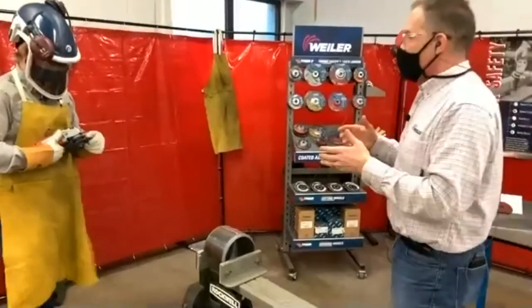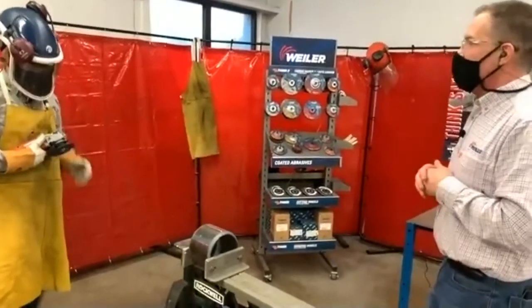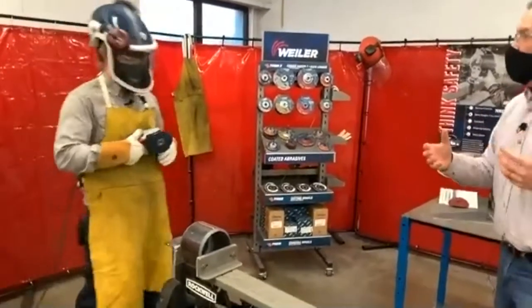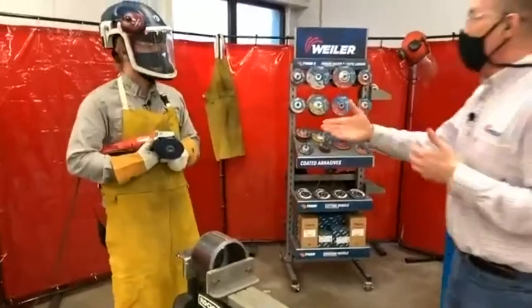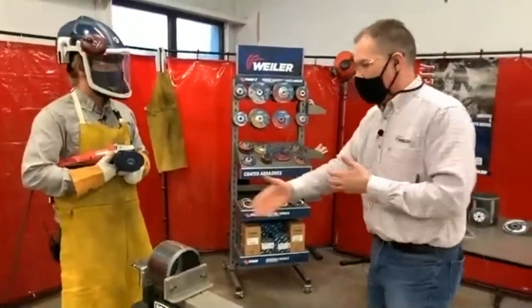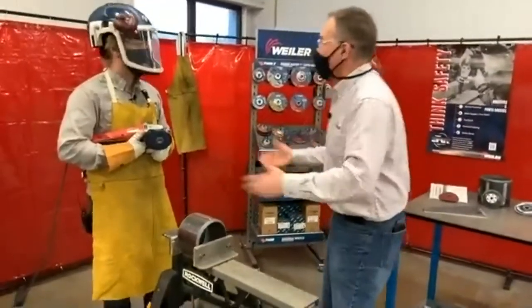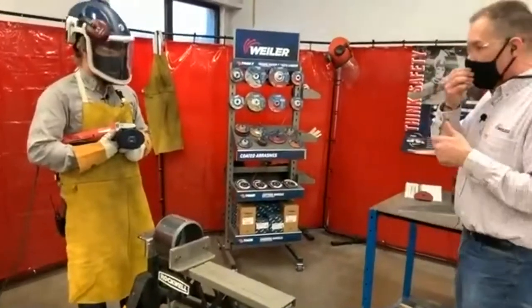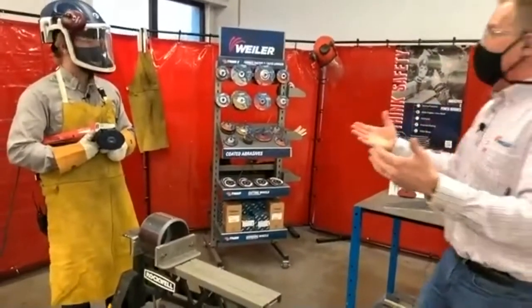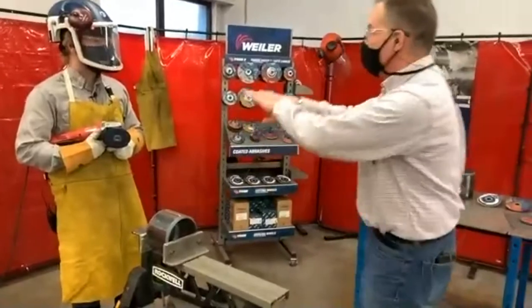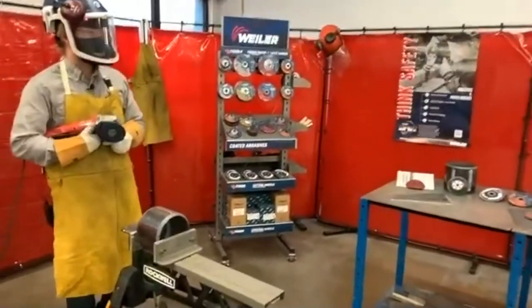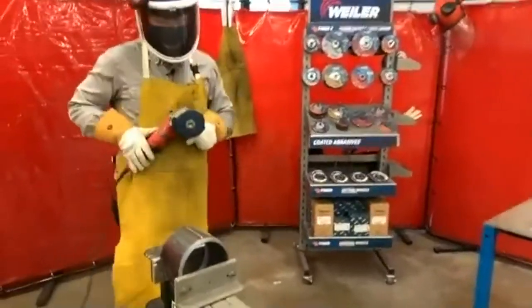And now again, the big difference here is this is our flexible backing pad, versus the medium or harder backing pad that we would use on a flat, more consistent surface. But again, it shows that you can get a high level of conformability while maintaining that wide contact patch with the appropriate backing pad.